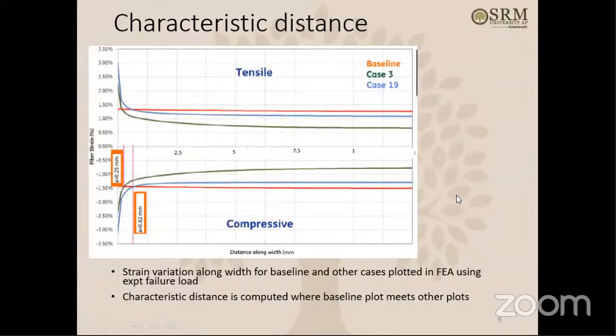Then, as you can see, the strain variation along the width for the baseline and other cases is plotted in FEA using the experimental failure load, and the characteristic distance is computed. So what is the characteristic distance basically? As you can see here, it is where the baseline plot meets the other plot. If you plot the strain variation, like tensile strain, how it varies along the width. Strain,